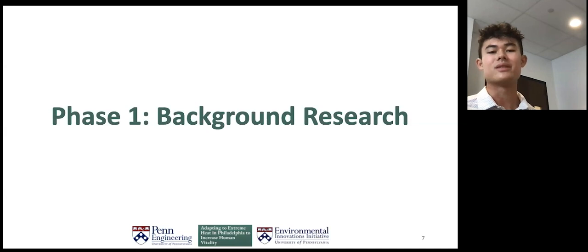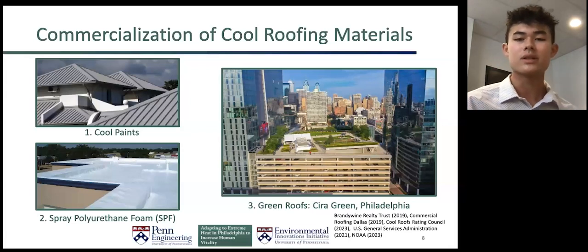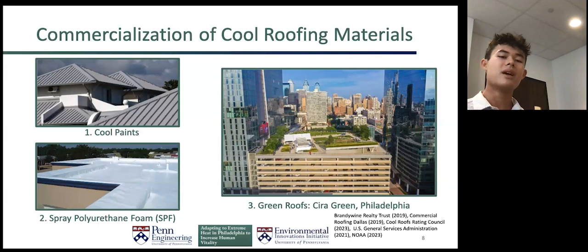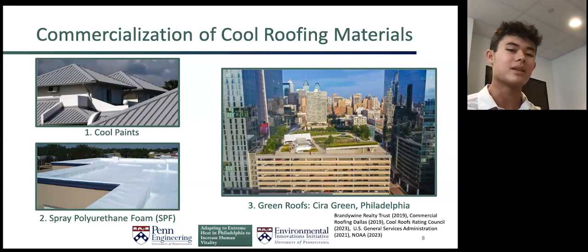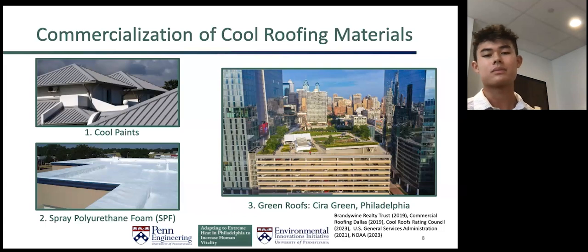The first part of my project this summer was looking at the existing approaches to cool roof coatings. So I started with commercial approaches that are already extensively used. And the first one is cool paints, which try to optimize the amount of light reflected and then also the amount of thermal energy that can be emitted from the surface. And this image shows how more recently colored paints have been developed, like the gray one on this roof that can still be classified as cool. And that's because almost 50% of the inbound solar radiation is in the infrared spectrum. So by using IR reflective pigments, you can afford to not reflect the entire visible spectrum, producing a color, and then you're still reflecting the majority of